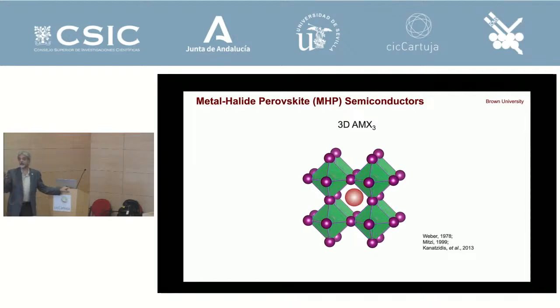Anyway, for people who are not familiar with the perovskite structure, so when the students here and postdocs here, this is the structure AMX3. This is the 3D structure, and M here can be lead or tin. Then you have X, which in ceramics is typically oxygen, but here we have halide, so that could be iodine, chlorine, or bromine. And then you have this A site in this cage, and this cage is actually quite large, and so none of the monovalent cations can fit in there. They rattle. And as anybody knows from beginning ceramics crystal structures, you cannot have rattling atoms inside a structure. It has to be snug, right?